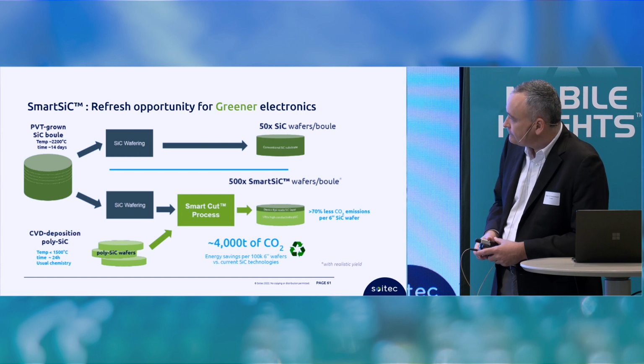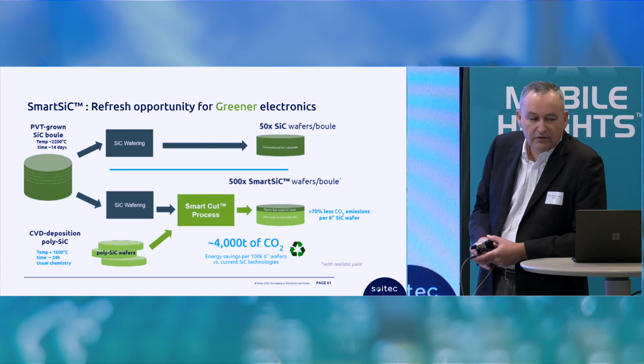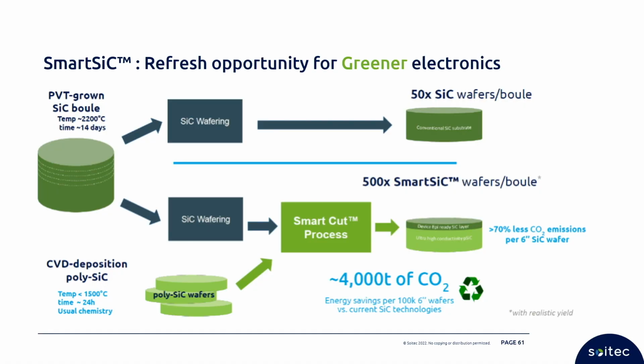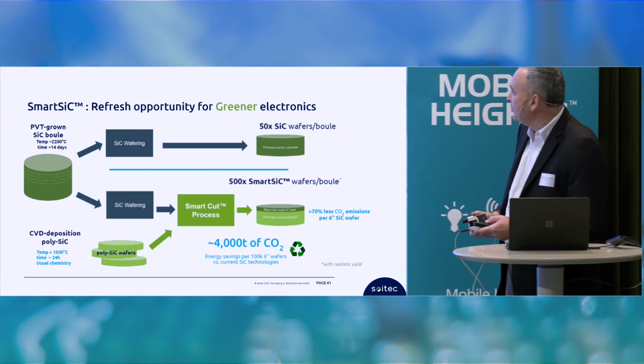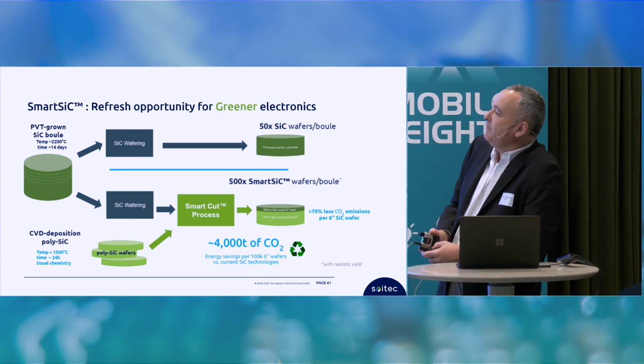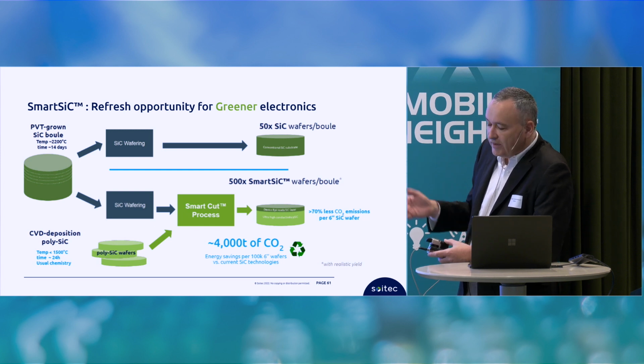Doing some mono SiC, you need to grow a boule. So the SiC world is totally different from the silicon conventional ingot. To grow a boule, high temperatures, very long times, and at the end, roughly 50 wafers per boule. With SmartSiC, we can consider these materials. It gives the donor wafers. We have a quite quick and easy CVD process to create poly SiC. We associate with refresh, meaning that with one boule, we generate roughly 500 SmartSiC wafers. So, a strong improvement regarding the availability of the product, and significant improvement in the CO2 emissions for the product.